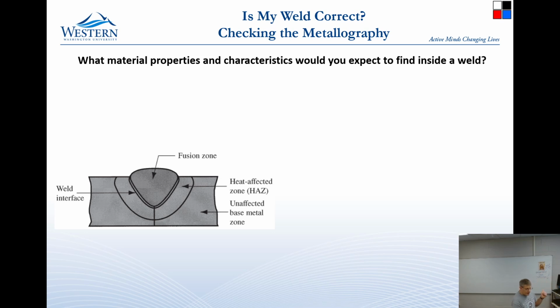Things that can really affect the heat affected zone is the abilities of the welder. If you have a good welder, they can weld quickly and not way overheat the material. And if you have a welder like me, then I can add a whole lot of extra heat to the material and cause a bunch of damage around the weld. And so when you have something that is critical, you end up using certified welders.